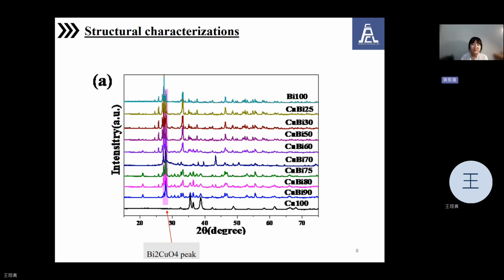And this graph compares the XRD of different proportions of copper and bismuth. There is a Bi2CuO4 peak around 28 degrees.